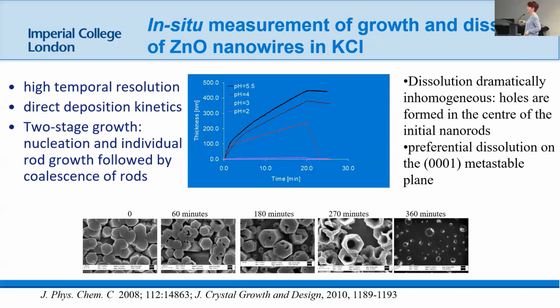If you put chloride in, it will stabilize that, right? It will screen the charge. But what happens when it redissolves is it doesn't just dissolve layer by layer by layer. It dissolves like a screw dislocation down into that. And that's because these edges are actually more stable. Right? So the edge is stable and the top is really active. And so you're able to get these beautiful